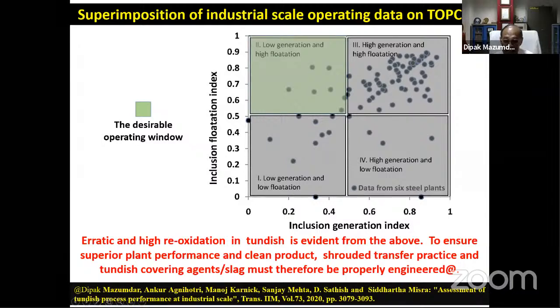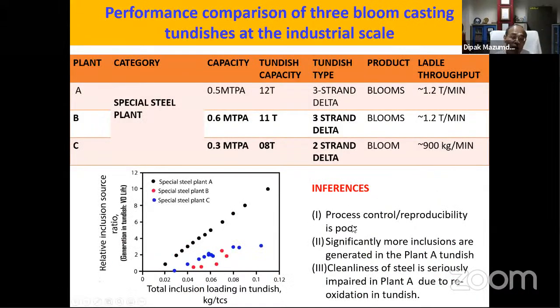This is again a very recent work which we have published in association with six different steelmakers in the country. If you compare, for example, three special steel plants, you can see that among them there is quite a bit of difference. They have the same sizes, same capacities, yet if you compare total inclusion loading, it's a huge range, which shows that these steel plants are not able to control their process well. Otherwise, I would have gotten this value in a narrow range itself. Similarly, these steel plants are relatively better than these steel plants, where we see that generation in the Tundish is significantly higher. So we can draw a series of conclusions from the formulae that have been advanced in this work.